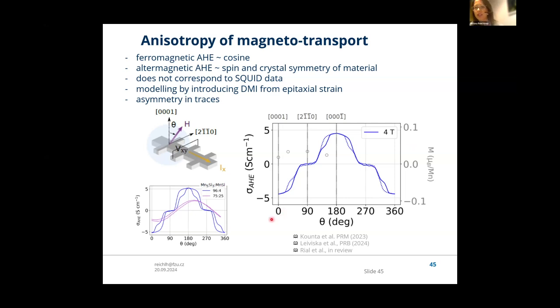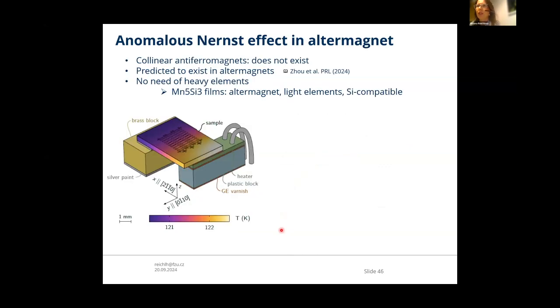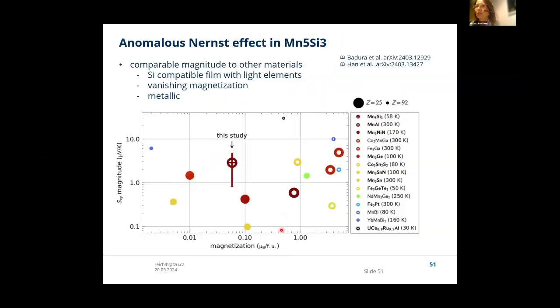Okay. So then I will skip the Nernst effect and just go to the summary. I will just show one last slide. We also looked at not only the anomalous Hall effect, but also at the anomalous Nernst effect. And what we observed was that in this material, although it's composed of very lightweight elements and it's a metallic system, so all these things which would normally act against a measurable and significant anomalous Nernst effect, we could observe a clear spontaneous anomalous Nernst effect.